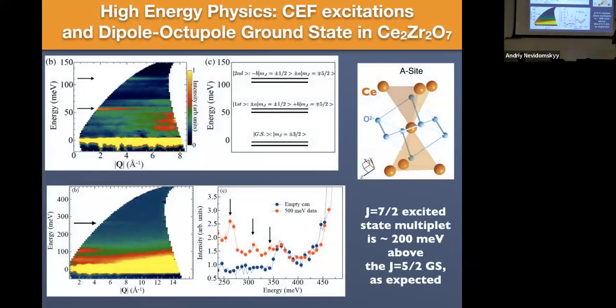What I'm showing you at the bottom is an inelastic neutron spectroscopy experiment where the energy scale that we're probing is about half an eV, right? 500 millielectron volts. It's not that easy to see, but the thing I want you to pay attention to is where this black arrow is pointing. You can see excitations within the J equals 5/2 multiplet here, but then the excitations to the next multiplet, which is J equals 7/2, are up here at about 250, 260 meV.